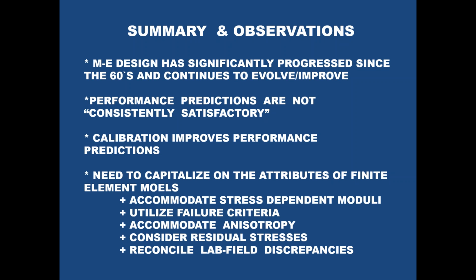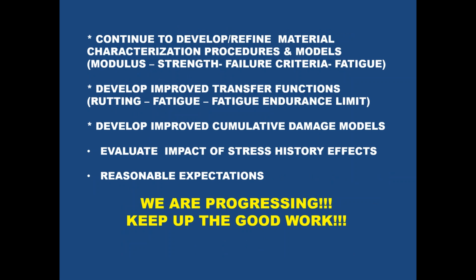However, we need to go to finite element models. We need to accommodate stress dependency. We need a failure criteria. The idea of anisotropy, residual stresses. We need to reconcile lab and field. Whenever you do a lab test and get a number, you do a field test to back calculate a modulus and you're off by a factor of 2, you say, wow, we must have a problem here. Okay, we need to continue to refine our characterization procedures for modulus, strength, failure criteria, and fatigue, improve transfer function.